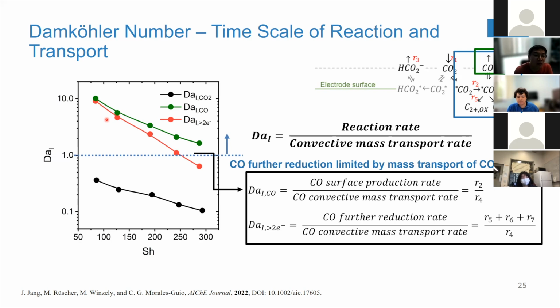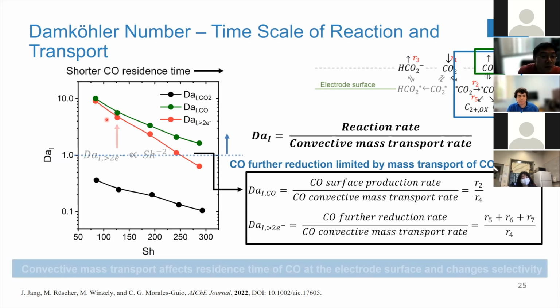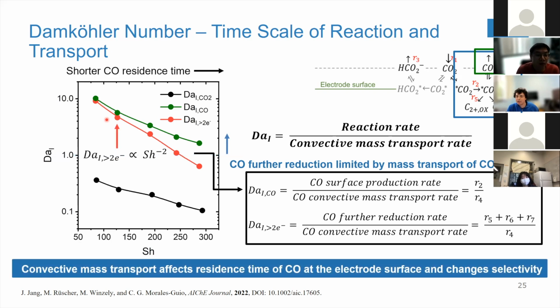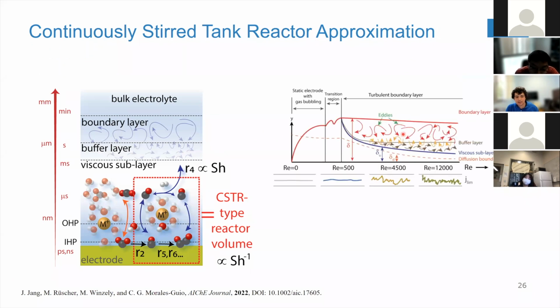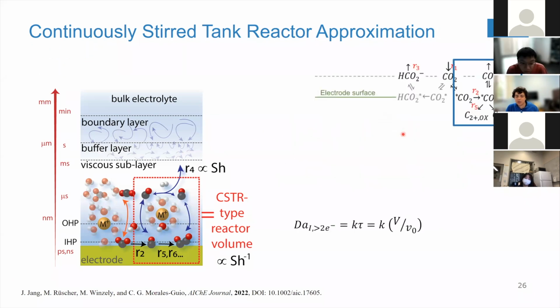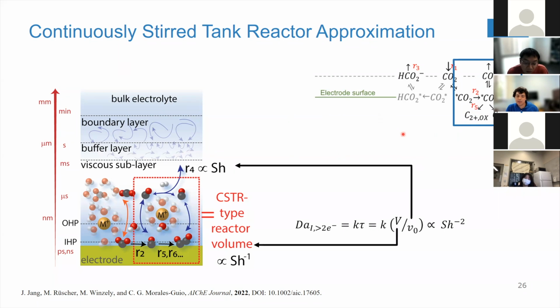So CO further reduction is limited by mass transfer of CO. And if we look at the further reduction, what we say is that this is actually 1 over Sherwood squared. So the reduction of CO to further reduced products is a first order process, and it's also a function of the residence time of that CO near the surface of the electrode. That matches the kinetics that you would expect for a CSTR volume.